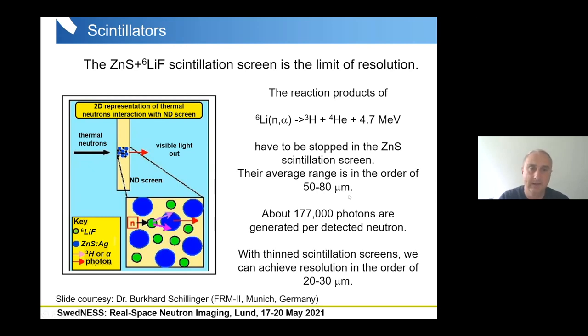So here are some facts related to the limitation of the resolutions. Actually, the mean free path of this triton is about 50 to 80 micrometer. And this is actually, let's say, the limitation. So if we use very thin scintillators, then we can go to resolution of 20 to 30 micrometer. And this is actually the best resolution which we can achieve with this type of scintillators.